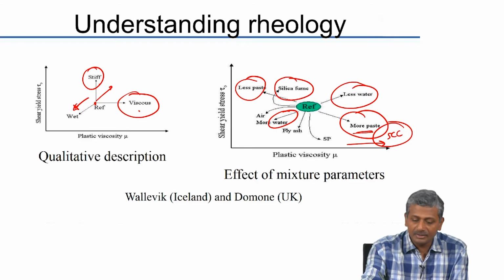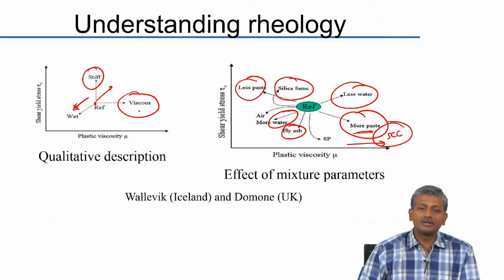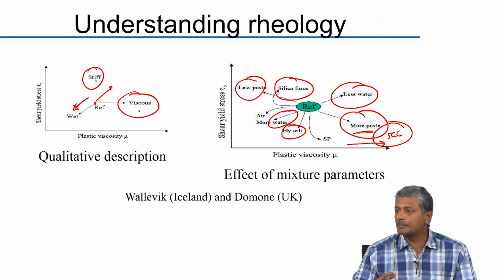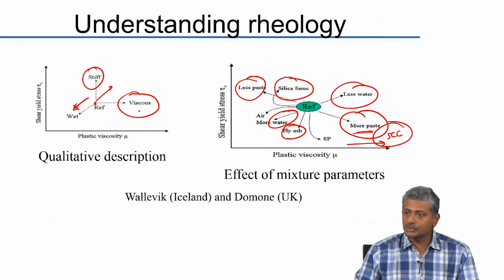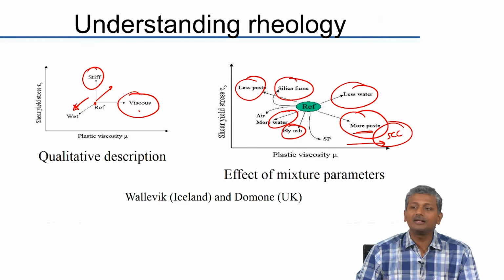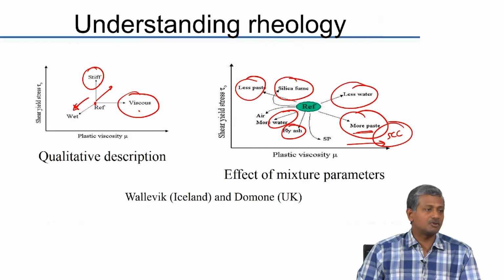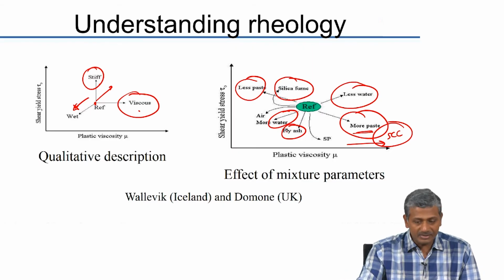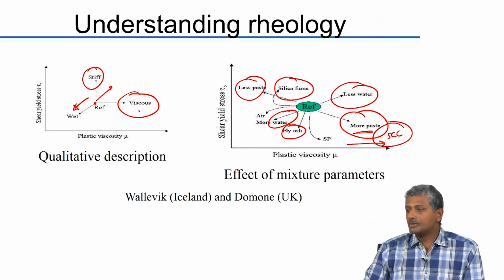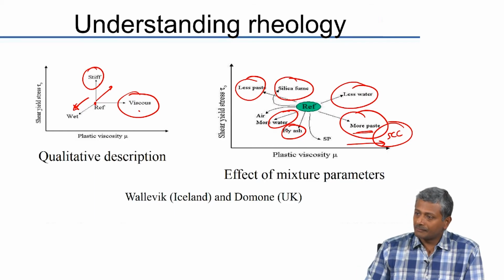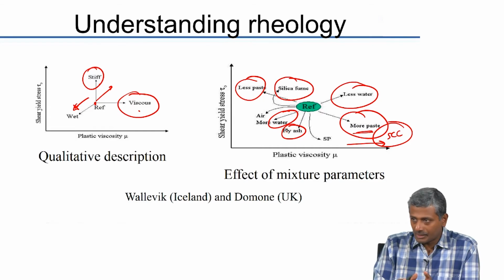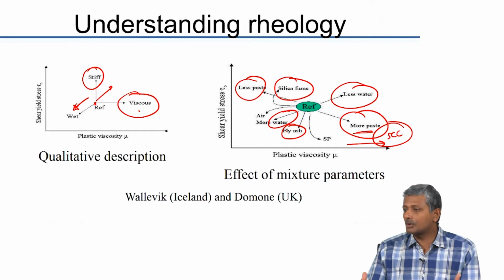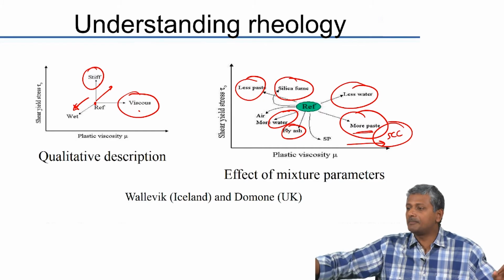Now, with fly ash, which is essentially spherical particles, your viscosity also comes down, right, because of the sphericity of the particles. Secondly, because fly ash has a greater volume as opposed to cement, when you replace cement with fly ash, you are increasing again the spacing between the aggregates. So, your yield stress also will tend to come down. So, when you have more paste, it will still flow the same extent, but it will start flowing very slowly. Because of the cohesion, it does not spread immediately.